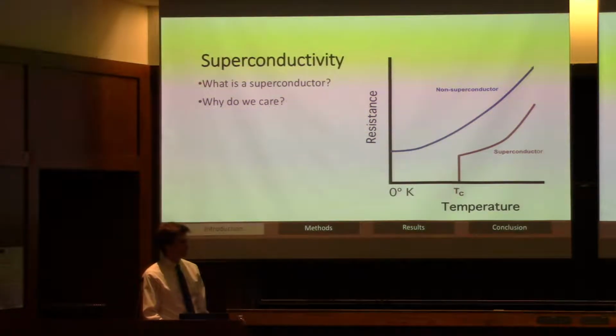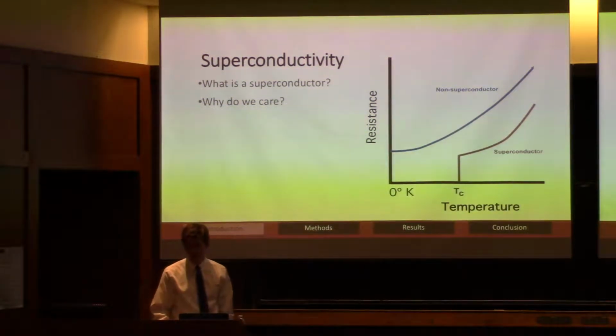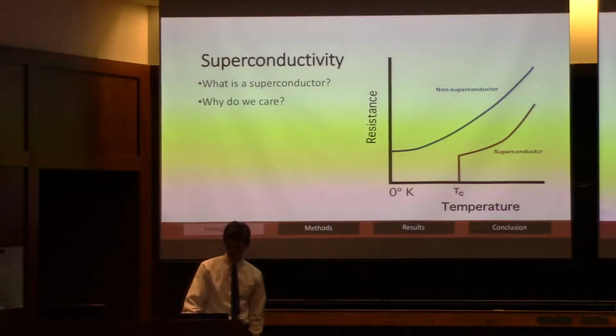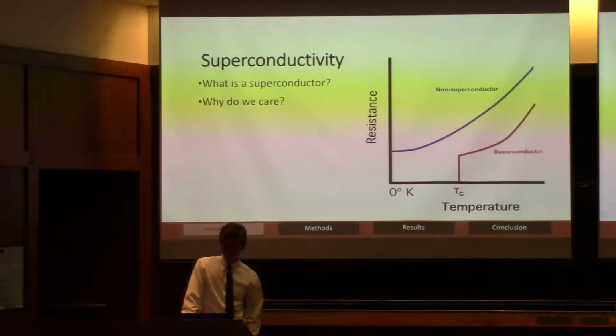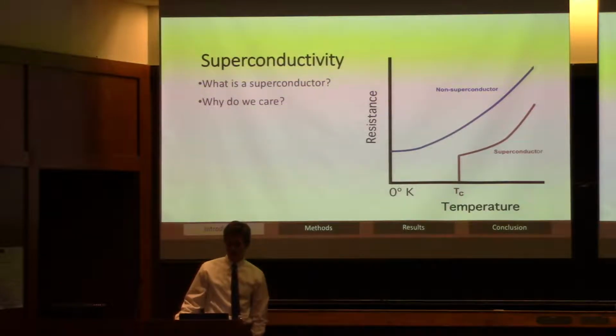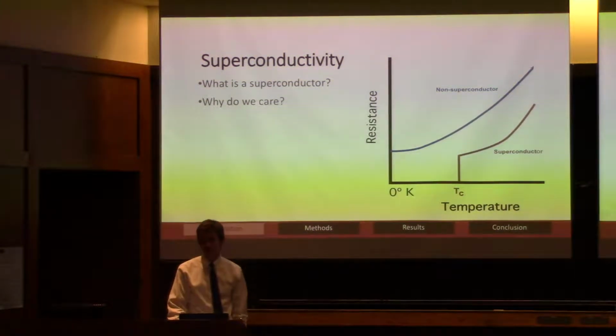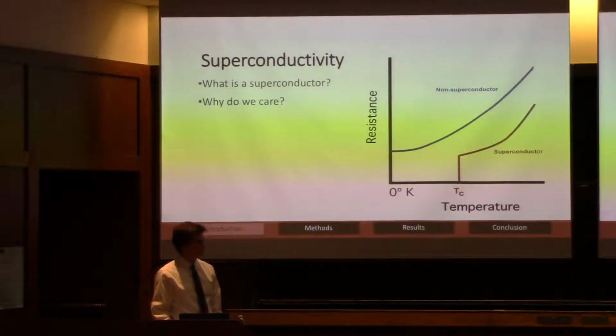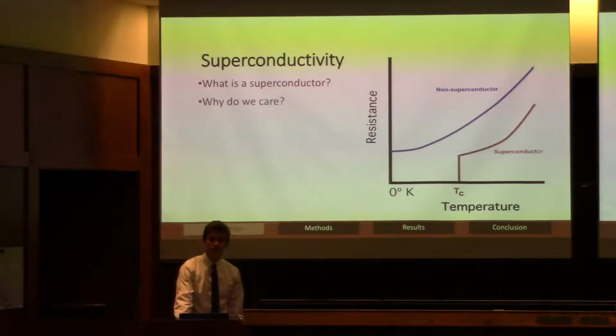So when you hit the critical temperature, when you're cooling down your superconductor, it starts to display absolutely zero electrical resistance. So this means that when you put a current in a superconducting wire, that current will continue indefinitely with no power loss. But the problem with that is these critical temperatures are extremely cold, on the order of single digits Kelvin. So we can cool our samples down to 5 Kelvin, which is negative 450 degrees Fahrenheit. So that's really, really cold.